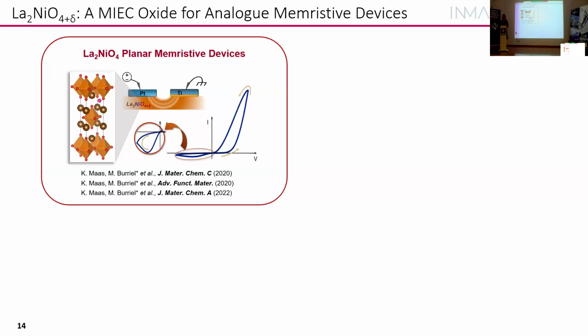Okay, so now these are the first results. When we started working with these materials, we started working with epitaxial films. So we grew them on single crystal substrates. And then what we put was the 2 electrodes on the top of our material. And we started with platinum and titanium. So we already had a nice analog type switching here.